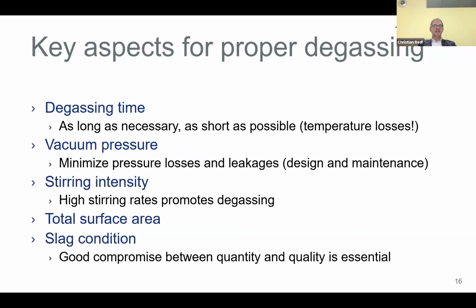The stirring intensity, you stir with a bottom plug, argon stirring usually. So high stirring rates, of course, promote the degassing efficiency. Degassing efficiency is, of course, also influenced by the total surface area. This is something which you can influence to a certain extent.